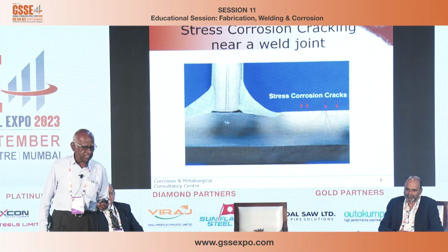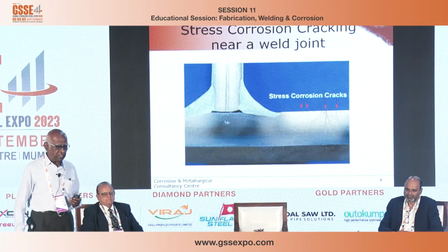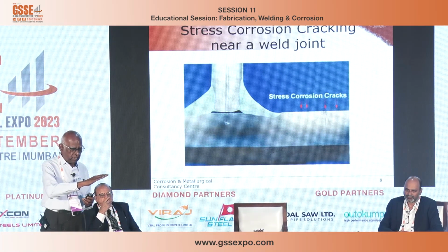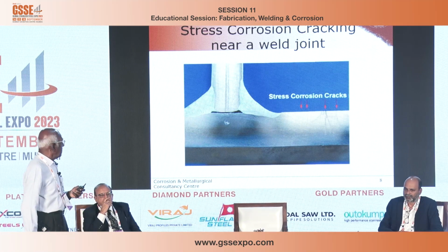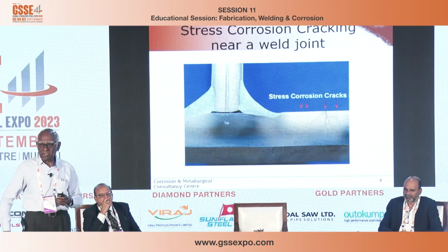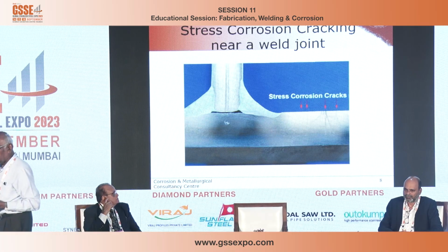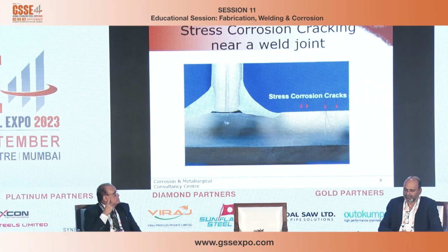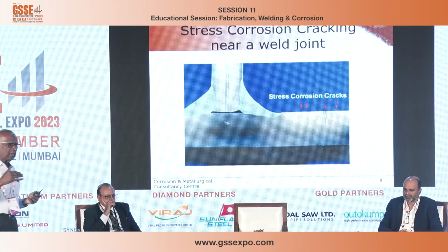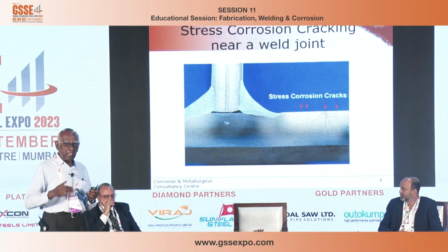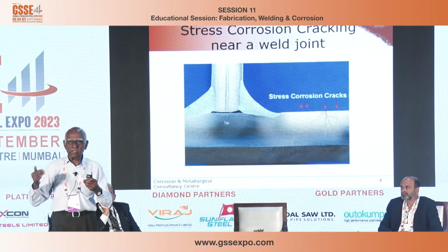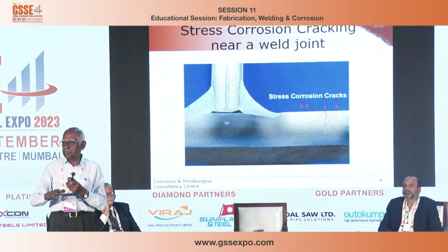That is the reason I mentioned this. You can see stress corrosion cracking. You can see absolutely no corrosion, no wall thickness reduction, but on the right hand side, fine cracks have developed. These are called stress corrosion cracks. The corrosion happened at a localized place near a weld joint and residual stress. So all these are important.